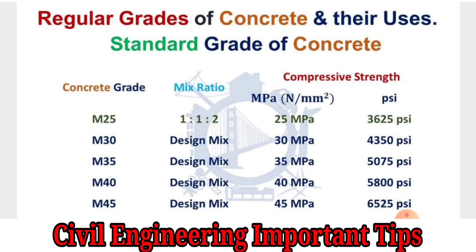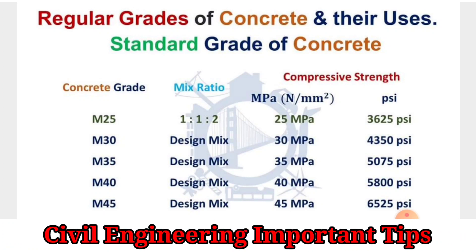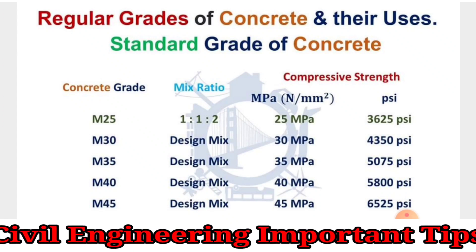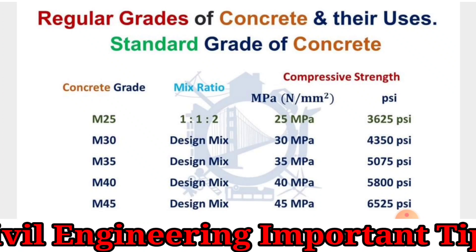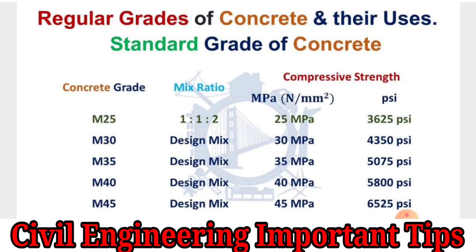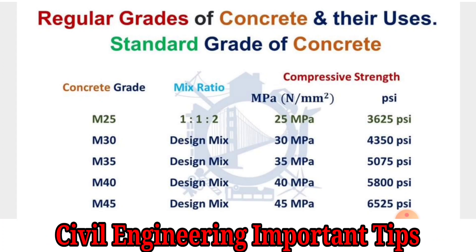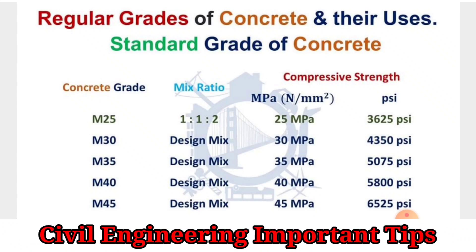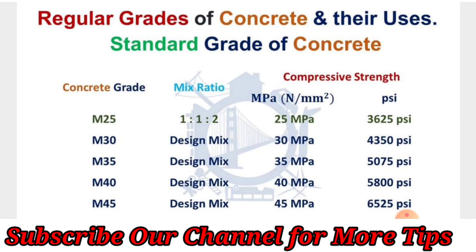For M30 and above, we have to perform mix design in a lab, adding admixtures like plasticizer and micro silica. After 28 days, M30 achieves 30 MPa. From M30 to M45, mix design is required, and grades like M35 are used for precast panel works.